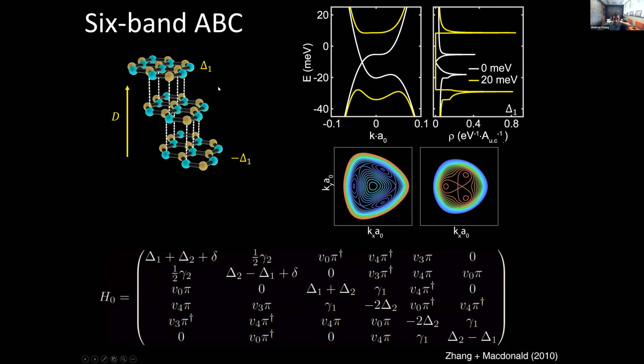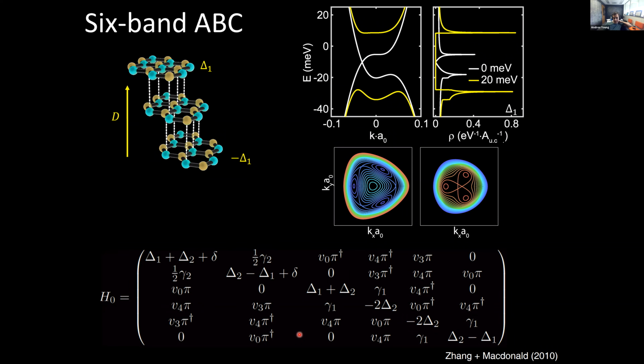Okay, you can look at more details. This is what that band structure looks like within a model. Here are contours of the Fermi surface. This is when you account for not just the simplest model, but actually all the different ways that electrons can hop between layers and within a layer. So you get something much more complicated where you account for all 6 atoms in the unit cell. But the basic physics is the same, in that you have these divergences in the density of states, which are enhanced as you put a larger and larger electric field across these 2 layers. These Van Hove singularities also take on a little more the character of saddle point Van Hove singularities rather than band edge Van Hove singularities, for those who are interested. But the point is that you can create the situation experimentally where you have very large density of states, and then ask yourself what happens.